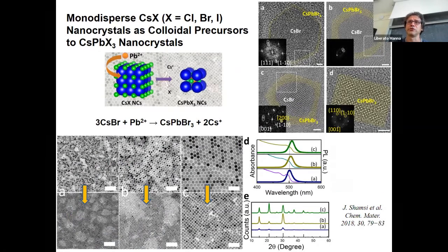Another similar transformation is the synthesis of perovskite nanocrystals starting from cesium halide. In this case, we show the example of cesium bromide. You start from cesium bromide nanocrystals of different sizes, you react them with a solution of lead oleate, and you get, starting from the surface of the nanocrystals, a partial cesium to lead cation exchange, which continues all the way to the center of the nanocrystal, transforming them into perovskites. Again, this is not as simple as it seems. There is also some etching of the nanocrystal involved, but it's a nice partial transformation that starts from the surface and converts initial nanocrystals into another metal halide lattice.